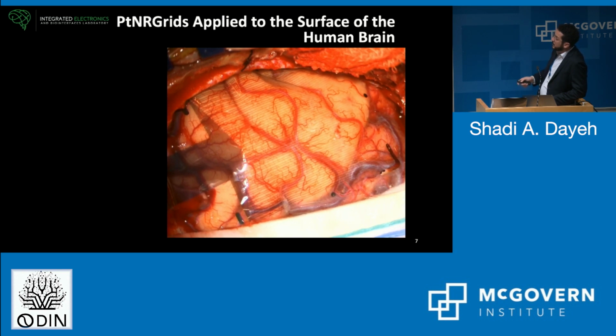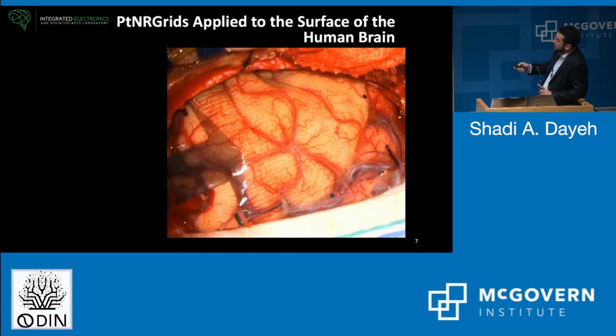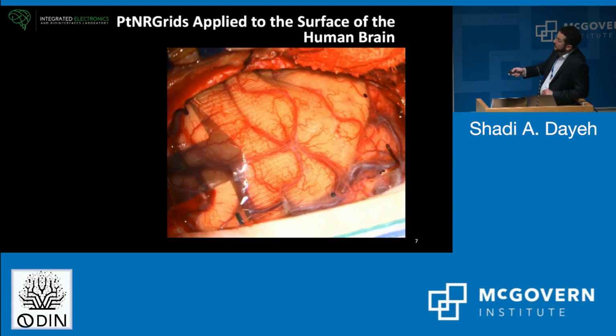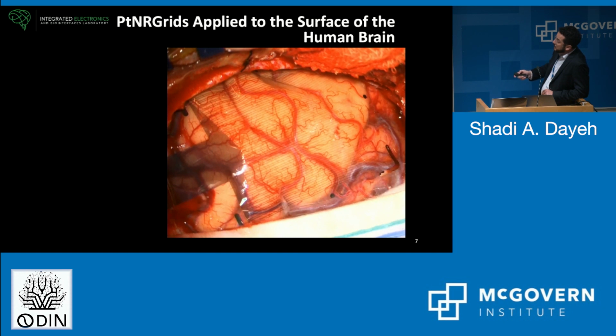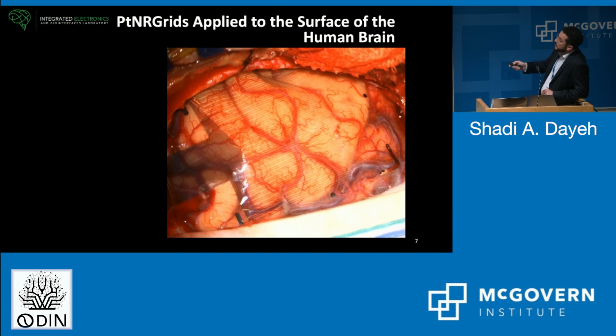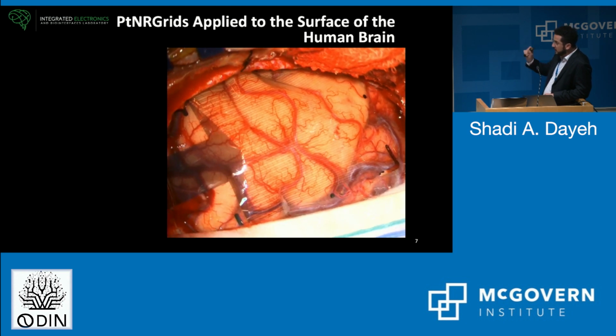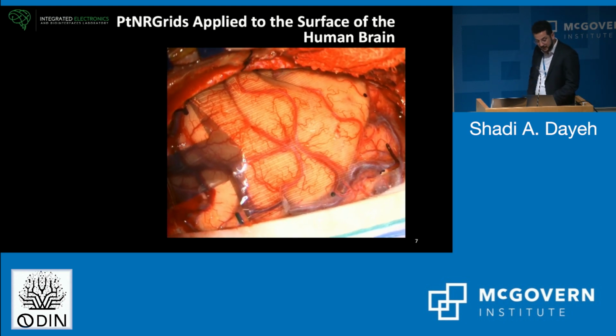Now here we're looking at a 1024 channel grid placed on the surface of the human brain during a neurosurgical procedure. You can see the contacts very well. You can see the metal traces to these contacts, and these are the boundaries of the grid. This is 3.2 by 3.2 centimeters squared. It's about 6 microns thick, so it's highly conformal to the curvature of the brain. It's also compliant to the brain motion, and this allows us to have a mechanical lock or stability between the contacts and the cortical surface, and therefore attain stable and high-fidelity recordings.